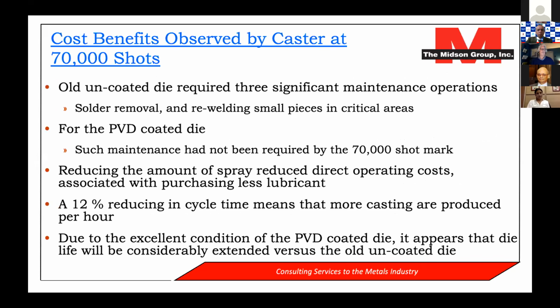So I talked about this a little bit earlier in the presentation, that the old uncoated die required 3 significant maintenance operations in terms of solder removal and then re-welding small pieces in critical areas. They had 3 significant maintenance operations by the time they got to 70,000 shots. With the PVD coated die at 70,000 shots, maintenance has not been required. The first maintenance was actually required at 75,000 shots.